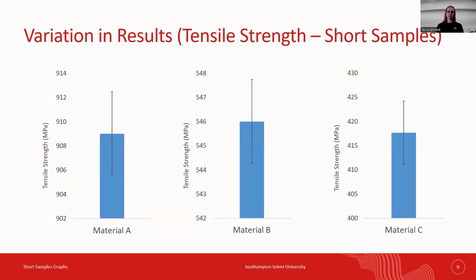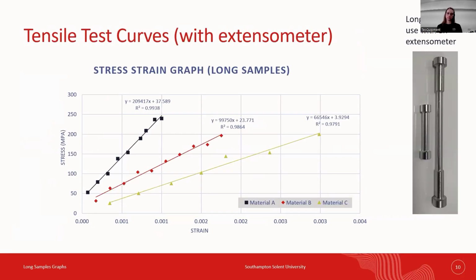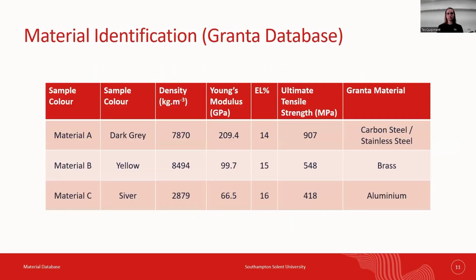We measured the tensile strength of short samples, and in our tests we observed variation in results. Some contributing factors such as machine accuracy, material defects, and slight misalignment during clamping added to the variation. An extensometer, along with the longer samples which are pictured on the right, were put into the tensile testing machine, which was then brought to a set force to ensure we stay within the elastic region, the data for which was used to calculate the Young's modulus. We compiled our data comprising of the material density, Young's modulus, elongation percentage, and ultimate tensile strength in this table.